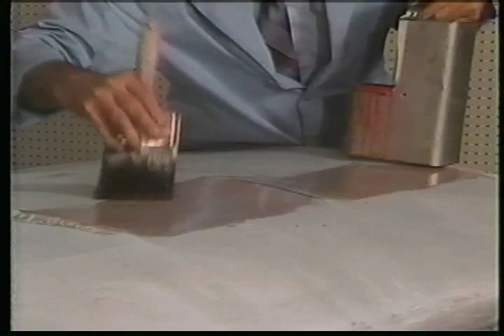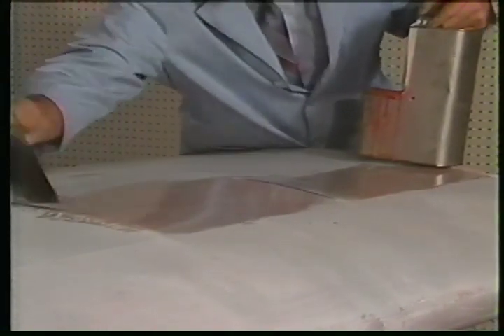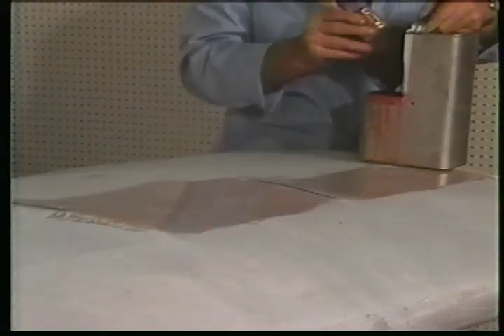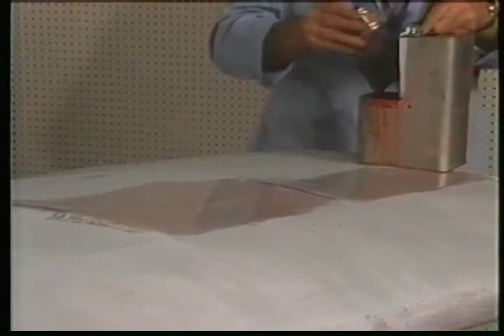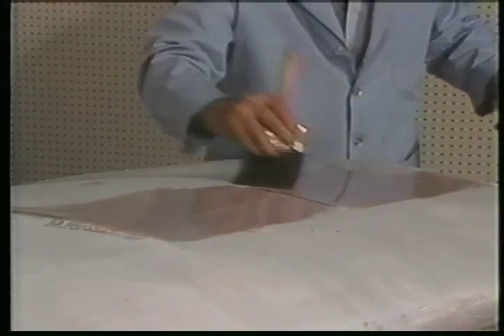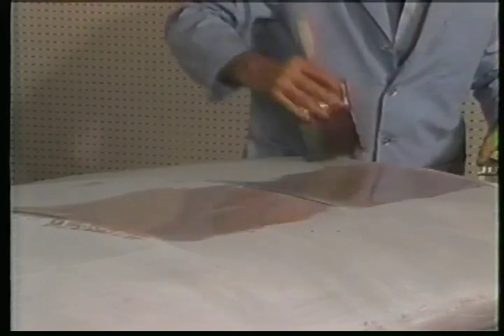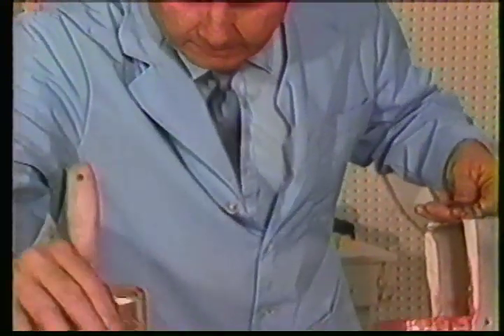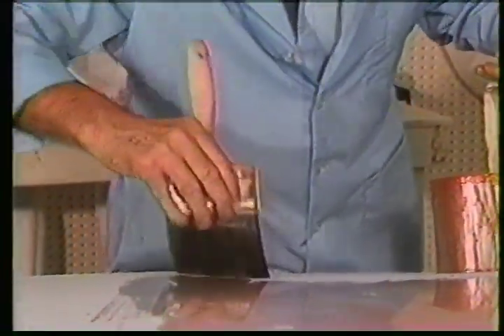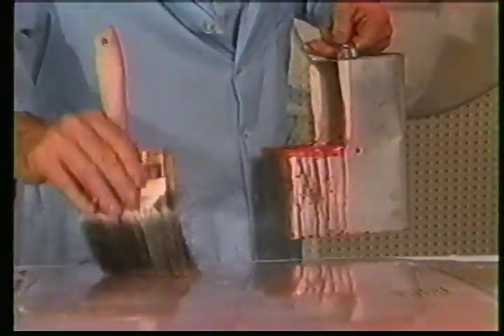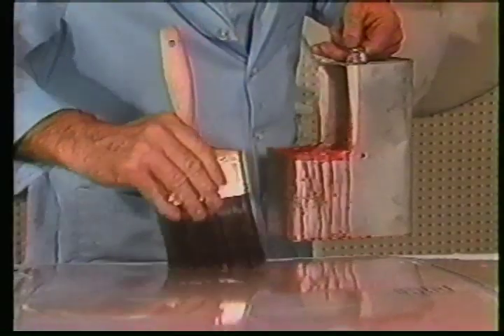Do not add polytack to polybrush to increase the adhesion, because polybrush already has all the adhesion needed, and the fast evaporating solvents in polytack accelerate the drying time of polybrush. Apply the polybrush in wet uniform strokes. Do not continue brushing after polybrush starts to dry, because it will rope or drag on the brush and may show as a rough surface through the finish coat. First coat brush patterns other than roping never show, because polybrush penetrates and levels with the surface of the fabric.